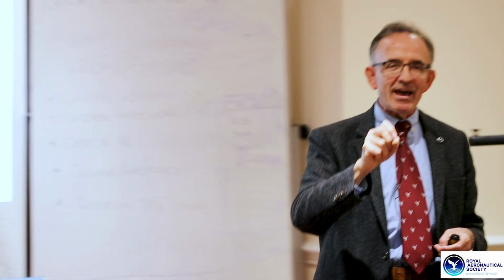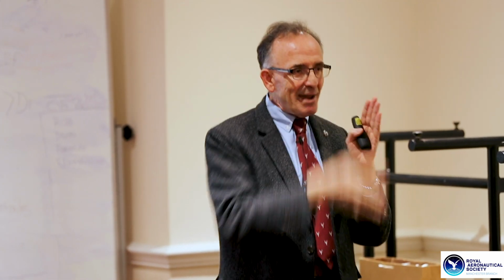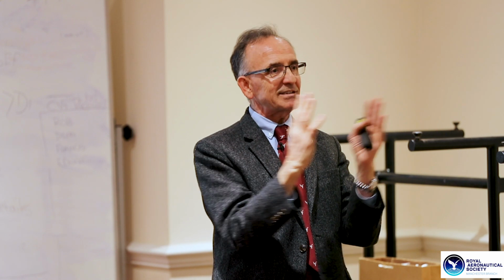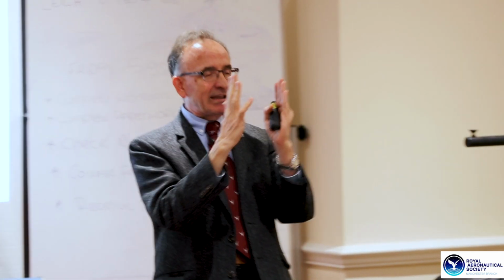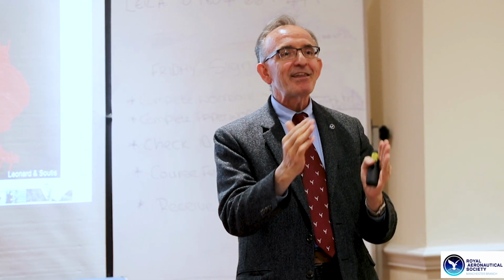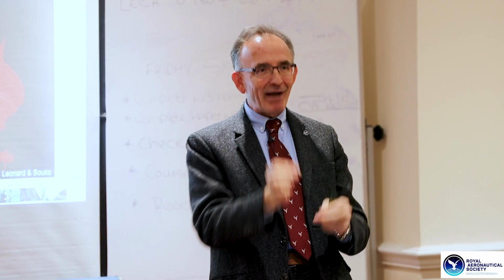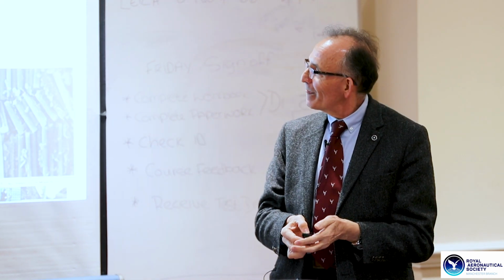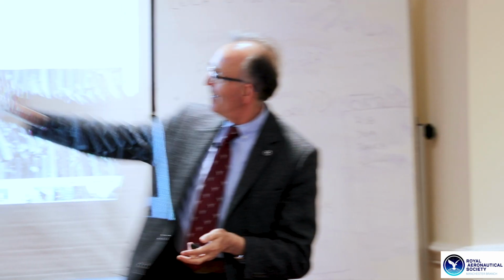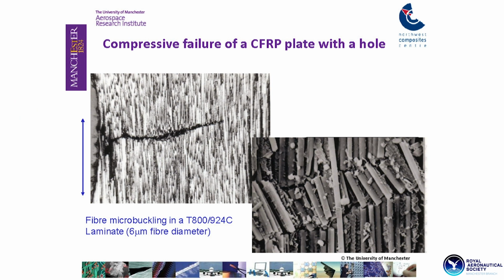And what is happening there is that the fibers, the actual fibers that carry the compressive load, have lost the lateral support, so the neighboring layers have delaminated, they don't support the zero plies anymore, and the fibers buckle at the microscopic level. That's the crack, and this is the fiber microbuckling. This is the axis that we load the plate, and this is how they break.